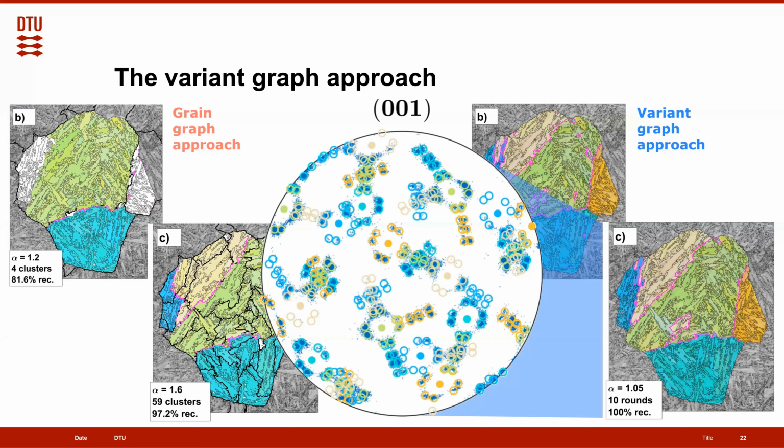And most importantly, in the end, if we look at all the martensitic orientations, these are the blue small dots in our pole figure here, and we see which martensitic variants are being contributed by the different austenite orientations, we can see that all the martensitic orientations experimentally have been accounted for by the reconstructed parent orientations that we've determined.